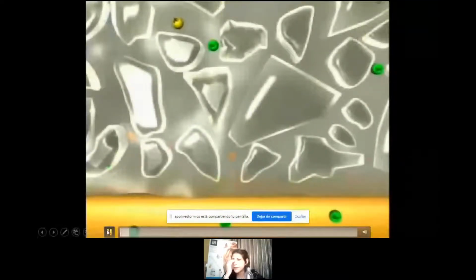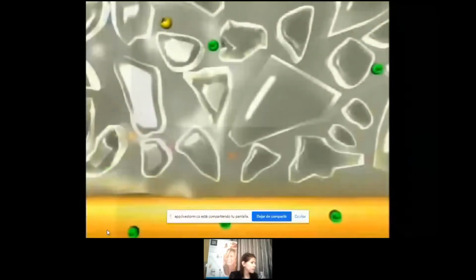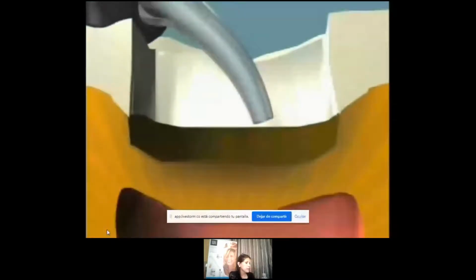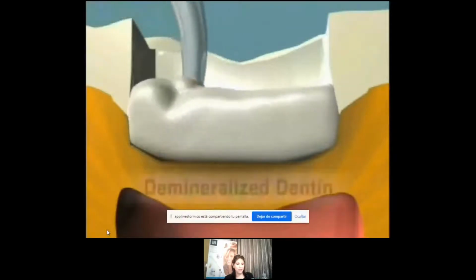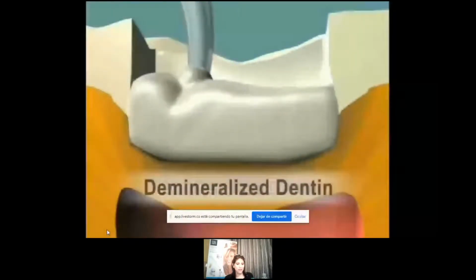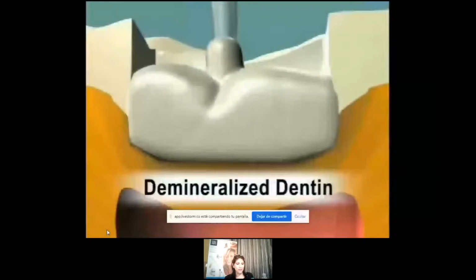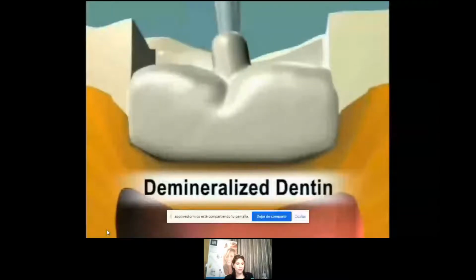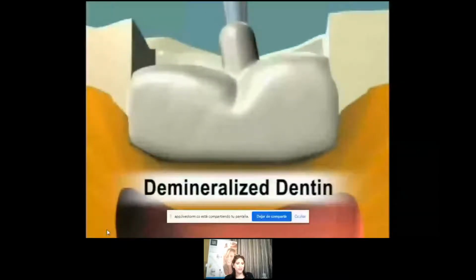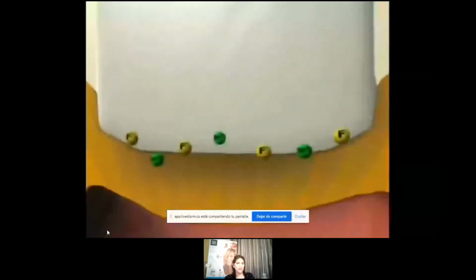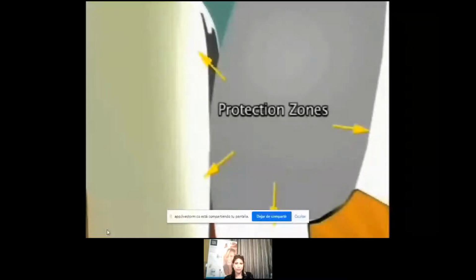The initial penetration of strontium and fluoride ions into the tooth helps remineralize and harden any demineralized dentin, which is covered by glass ionomer cement. Essential to the success is apatite-forming ion containing increased levels of fluorapatite. Glass ionomer cements therefore create zones of protection for surrounding tooth surfaces.